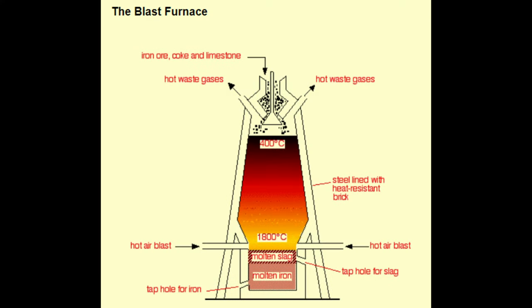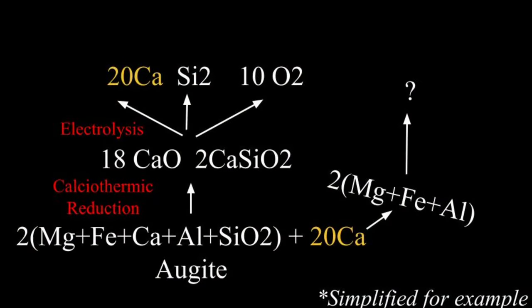This made me realize I had accidentally recreated the wheel, as this calciothermic pre-melting phase was functionally a solar blast furnace, using calcium instead of carbon coke. Even more, it turns out that the created byproduct, calcium silicate, is also soluble in the calcium chloride electrolyte we'd be using to remove the calcium oxide from the reduced alloy. Electrolyzing both these elements would yield calcium metal and pure silicon, which won't bind together without oxygen. With this process, we can reduce our regolith to an alloy using just calcium metal and solar energy, and even remove the silicon from this alloy.